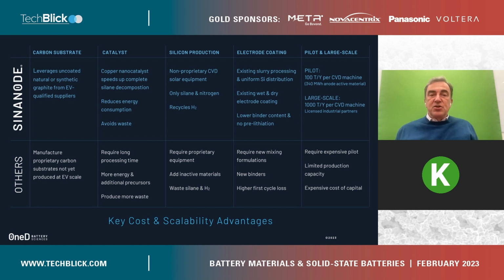At the end of the day, the production is inexpensive because the capex is low. It's less than $1 million per machine in large scale production. At small scale, it's less than $2 million per machine. And all of the hydrogen can be recycled to the silane plant because all the silane is decomposed into silicon. The electrode coating is compatible with dry electrode coating. We have more than 10 years of expertise on that.